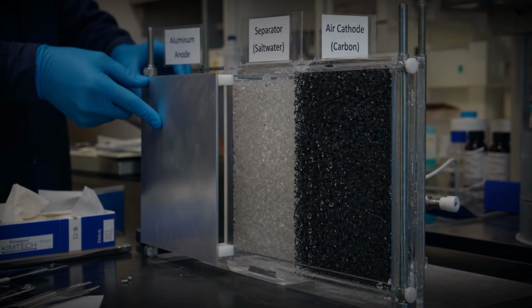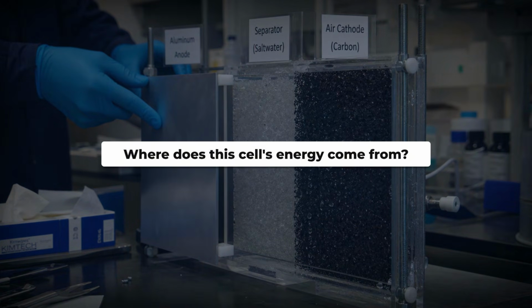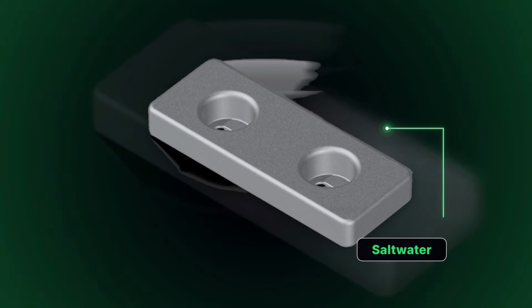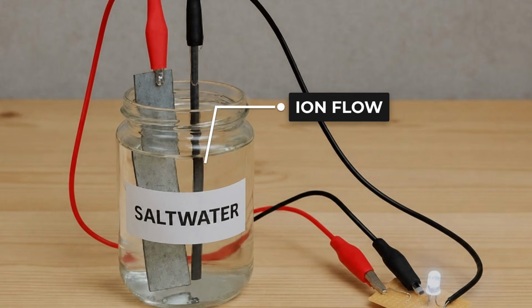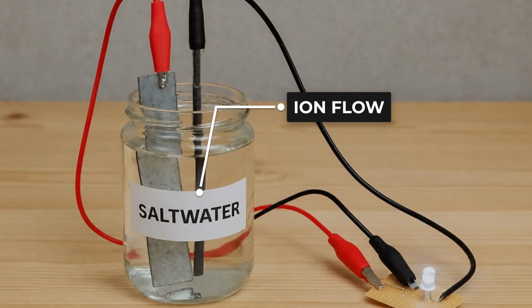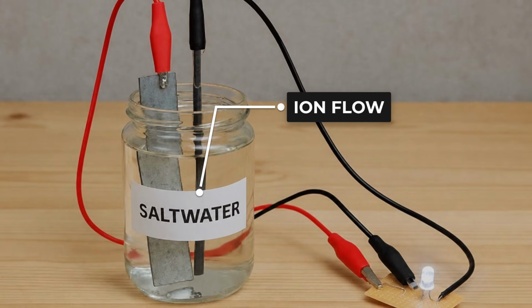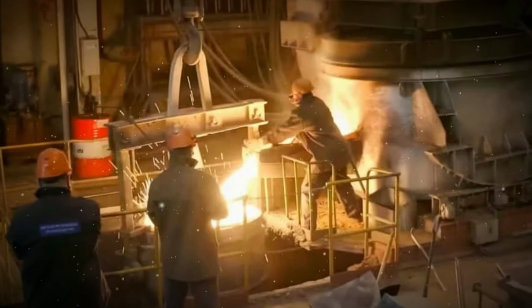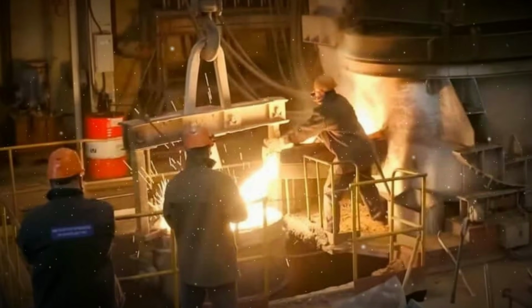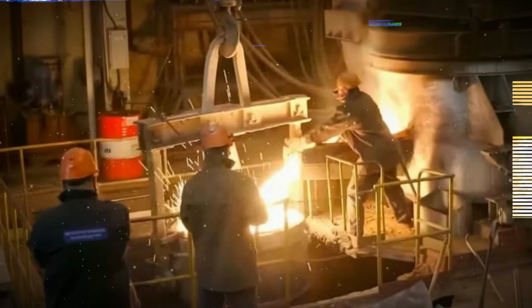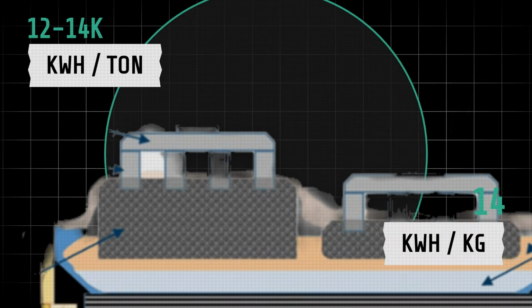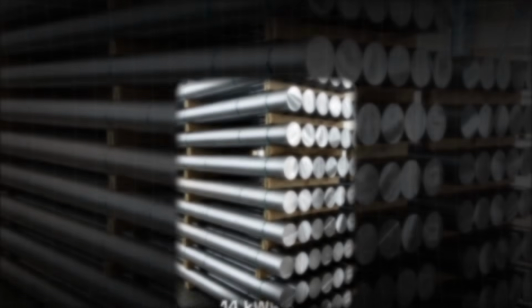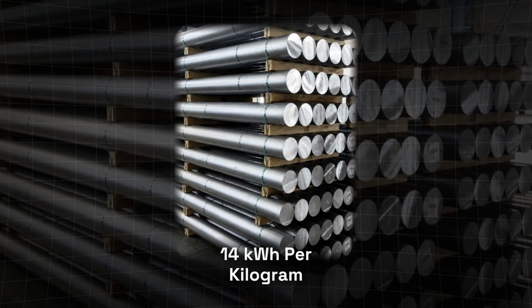So where does the energy in an aluminum air cell actually come from? Not from the air, not from the salt water either, which is doing nothing more than carrying ions from one side to the other. It came from a smelter, and somebody else paid for it a long time ago. Producing aluminum by the Hall-Héroult process consumes somewhere between 12,000 and 14,000 kilowatt-hours per ton. Divide that down and you get roughly 14 kilowatt-hours of electricity for every kilogram of metal.